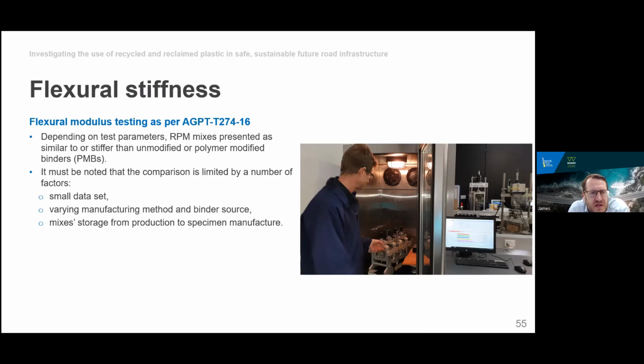So I guess one of the reasons why there's such a small data set to be compared is that there's a lot of different parameters that could be looked at, many different manufacturing methods and binder sources, and also potentially differences in whether it was laboratory produced mix or field manufactured mix. Obviously, another thing to consider is even the binder's storage stability in terms of making unmodified, polymer modified or recycled plastic modified binders for use in recycled plastic modified asphalt. Next slide, please.